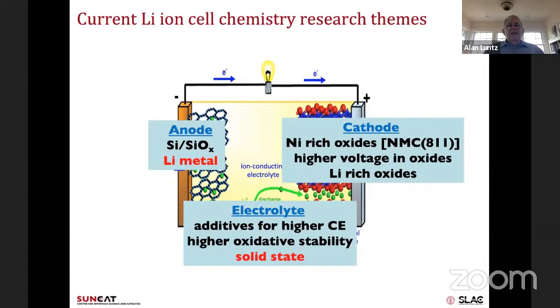The problem is when they take up this lithium, they expand dramatically, about 300 to 400%. And that either pulverizes the small particles that compose them, or at least keeps breaking apart the SEI, and you have to reform it all the time. Every time you reform it, you consume active lithium in the electrolyte. And so pretty soon you end up with a very low coulombic efficiency with these materials. So there's a lot of work trying to solve this problem of the volume expansion of the silicon or SiOx.